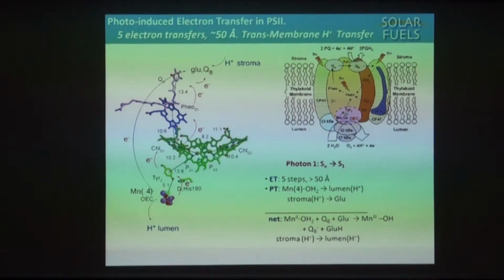It's unstable in this environment for any long period of time, but it undergoes rapid electron transfer from a phenol, this tyrosine. The tyrosine is hydrogen bonded to a histidine. It's actually a so-called proton-coupled electron transfer, proton transfer. That radical then, in a much slower time scale, starts the process of oxidative activation of the oxygen-evolving complex, 4 manganese and a calcium in a cluster. That oxidation then triggers proton loss.